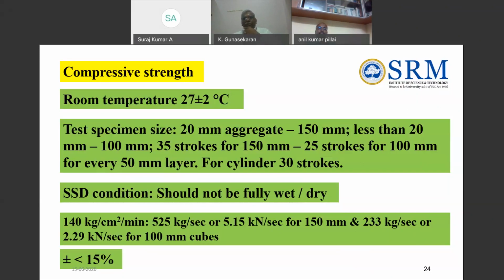Normally for this compressive strength, in Indian conditions we follow only the cube size, and in America they are using only cylinders. So when you are using 20 mm aggregate, you can go for the 150 combination, or if you are using less than 20 mm aggregate, then you can go for the 100 mm combination. Again, there is a problem in compaction. Suppose you are using normal compaction on your site, every time we go for only 25 strokes. That is not correct actually. If you are using the 100 mm cube, then only you go for 25 strokes. When you are using the 150 mm cube, then for every layer you have to go for 35 strokes. That is the standard. So 25 strokes is not a constant. It depends upon the size of the cube you are using in the lab as well as the site. Again, each and every cube should be divided into 50 mm layers.